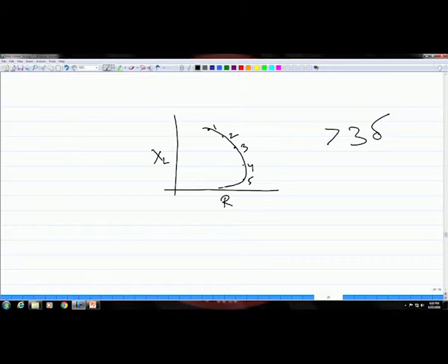So, at this particular depth or thickness, you can call the sample a thick sample, beyond which the eddy currents will not be able to penetrate, because at such thickness, more than 3 delta, the magnetic field of the eddy current will be completely trapped by the thickness of the material. That is why this thickness with respect to eddy current is called a thick sample, beyond which you will not be able to penetrate the eddy currents. So, this is the effect of sample thickness.